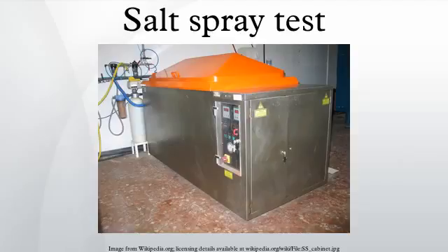Hot-dip galvanized surfaces are not generally tested in a salt spray test. Hot-dip galvanizing produces zinc carbonates when exposed to a natural environment, thus protecting the coating metal and reducing the corrosion rate. The zinc carbonates are not produced when a hot-dip galvanized specimen is exposed to a salt spray fog, therefore this testing method does not give an accurate measurement of corrosion protection.